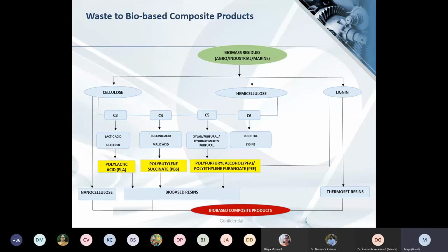And then from lignin, what can you get? Lignin is, as I've mentioned before, an aromatic macromolecule. It's composed of phenolic moiety, so you can extract bio-based phenolic resins from lignin. The other thing that you can do with lignin is, it has a highly cross-linked structure, so it has inherent flame retardant properties, and you can use it as a filler in composites. So based on the different materials that are derived from the waste, and again by different combinations and permutations, you can get a number of novel bio-based composite products all derived from waste.